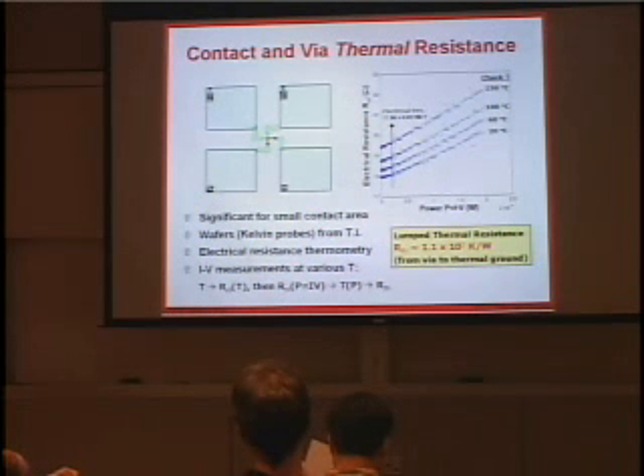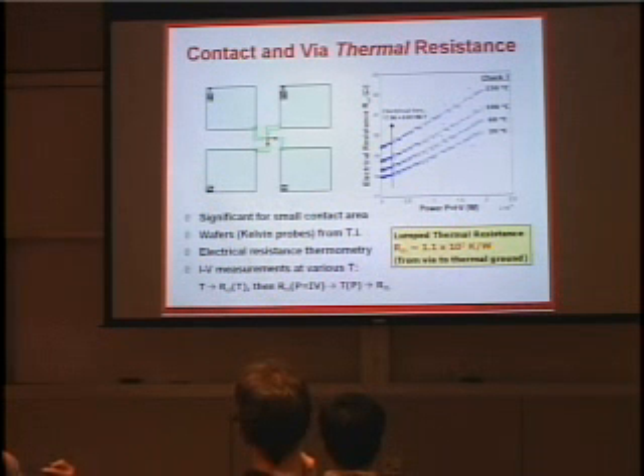Then you can also pump more current through these contacts, so you can measure the electrical resistance as a function of power, which is what I'm plotting over there. Then you can correlate this power with the temperature you were doing these measurements with. So you have a relationship between temperature and power. If you have that, you have the thermal resistance of the contact, and that's what I'm extracting here. This is a lumped thermal resistance between the contact and the thermal ground, but it is the thermal resistance that I'm using in this model.